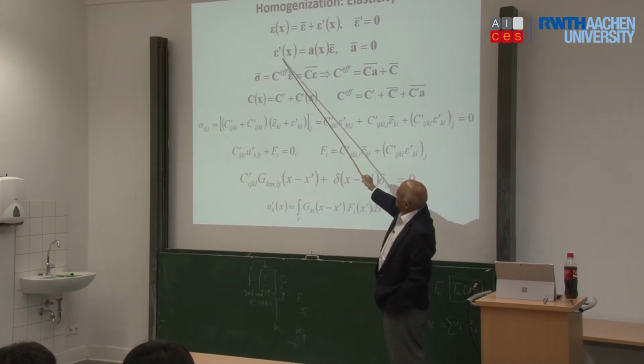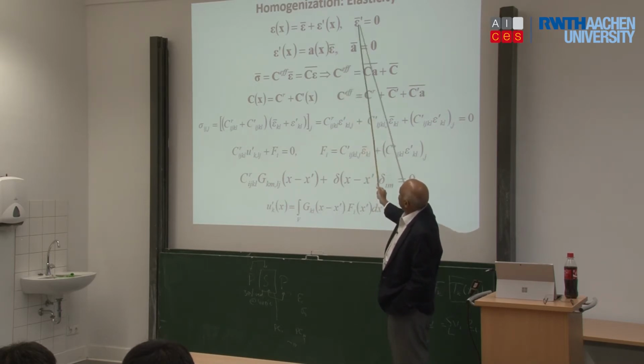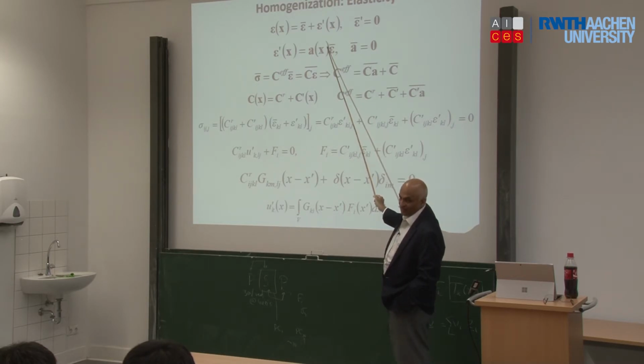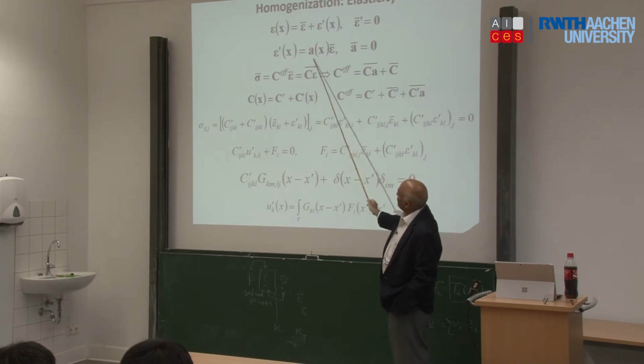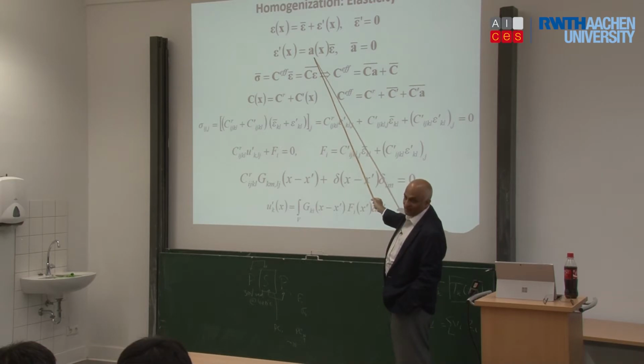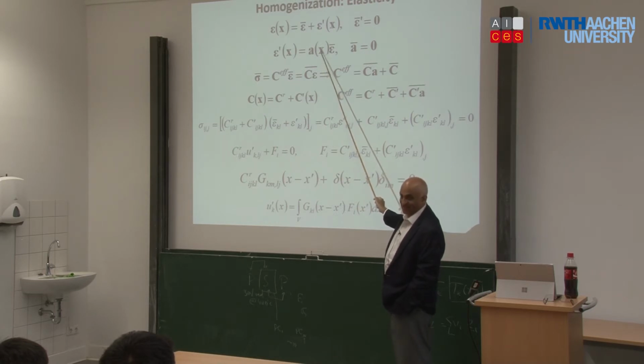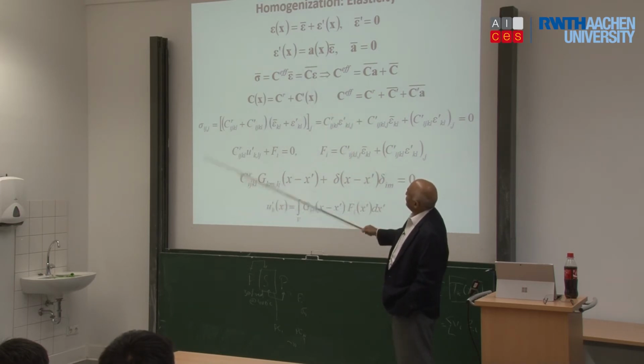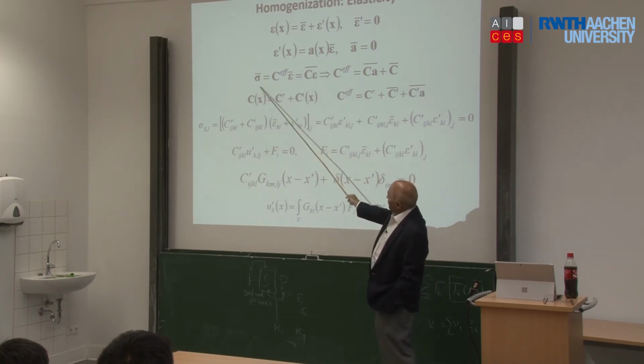Then I can convince myself that the perturbation at every point x depends on the macro imposed strain. This is a macro. Anytime you see a bar at the top, it's a volume average quantity, right? So if I impose a certain average strain at the higher length scale, the perturbation in the local value can be related through a fourth rank tensor, and this is called a localization tensor. So you have to first prove that this exists, and they have gone through the proof. They have shown that it exists, and once that exists, then you can say the effective stress.